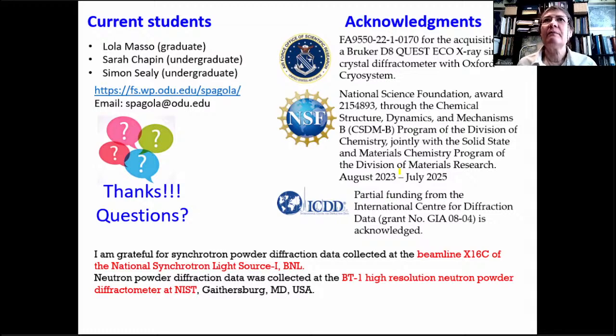Well, mechanochemistry would lead to one or the other polymorph by using a particular liquid additive in sufficiently large quantities, at least from the mortar and pestle that I used at that time. In many cases from solution, one can obtain mixtures of those. And the people that studied these compounds a long time ago could not grow crystals sufficiently large of the black form to solve the structure from single crystal diffraction. So the structure remained undetermined until we could prepare the pure form by mechanochemistry and solve the structure from powder diffraction data.